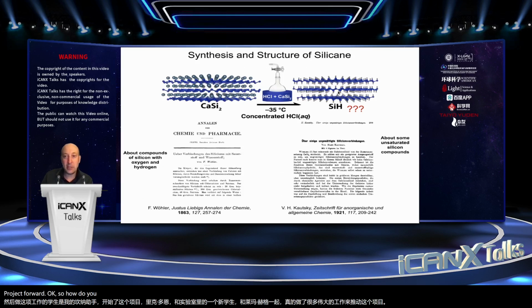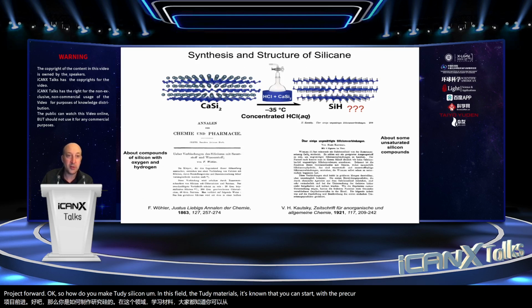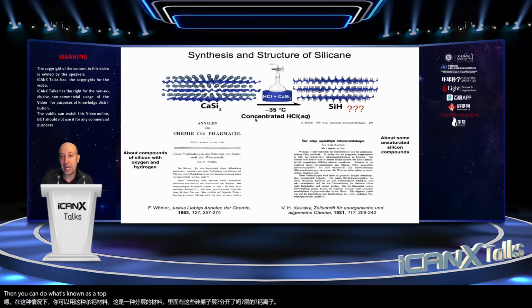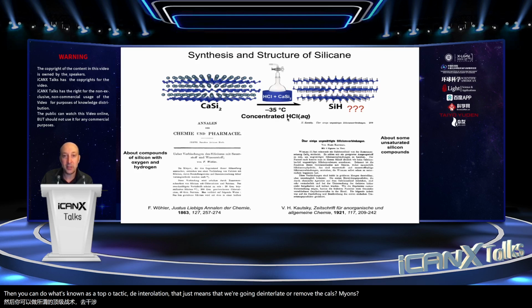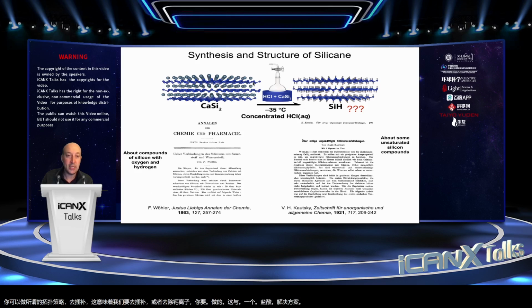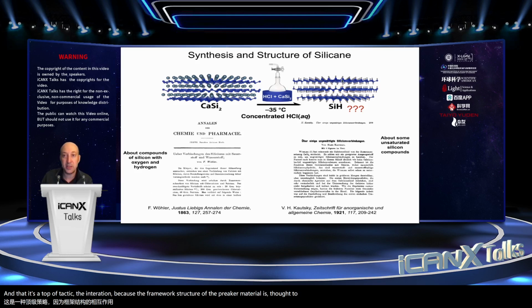Okay, so how do you make 2D silicon? In this field of 2D materials, it's known that you can start with the precursor that has a similar structure to the final material that you want. So in this case, you can take this calcium silicide material, which is a layered material where you have these layers of silicon atoms separated by layers of calcium ions. And you can do what's known as a topotactic deintercalation. That just means that we're going to deintercalate or remove the calcium ions. You're going to do that with an HCl solution. And it's a topotactic deintercalation because the framework structure of the precursor material is thought to be preserved after the deintercalation reaction.